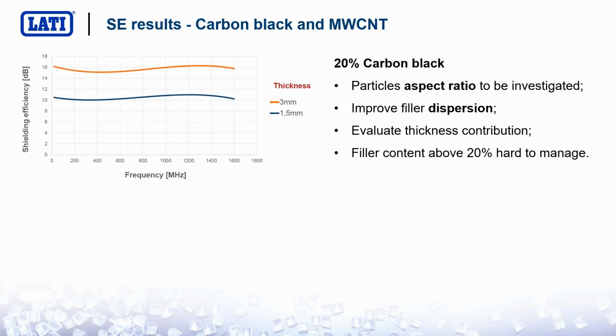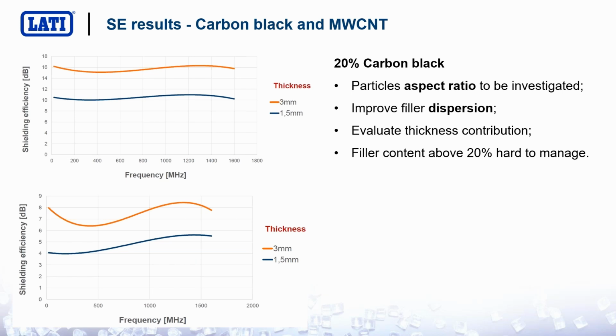The same issues were detected with carbon black and carbon nanotubes. With carbon black, particle quantities and aspect ratio are very important. It's very important to improve filler dispersion. The measurements we saw from a shielding efficiency point of view were very similar to graphite, so were not actually acceptable, less than 15 dBs, which is really quite small.